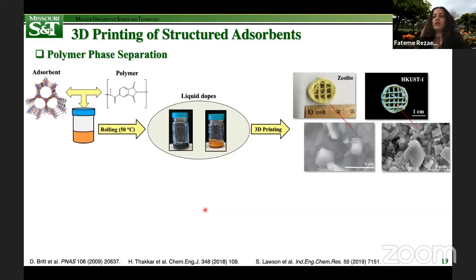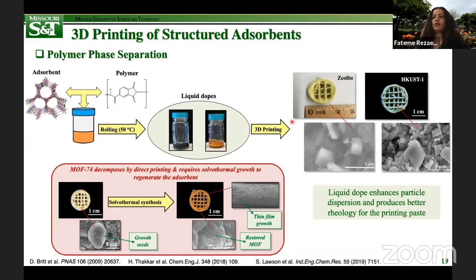To develop adsorbent structures through suspension in a polymer dope, these adsorbent particles are first dissolved in a polymer, right here, and then rolled under a heat lamp until a homogeneous dope could be obtained. Then the polymer adsorbent is precipitated out by dropping into a non-solvent through the 3D printing method, followed by activation and solvent removal. This method has been successful for zeolites 5A and zeolite 13X, as well as some MOFs, such as HKUST-1.